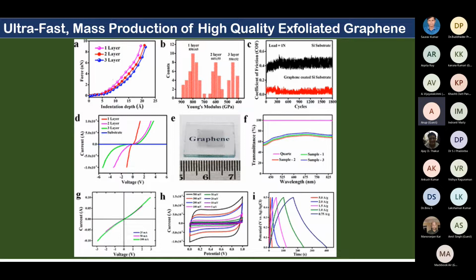But for the uncoated black one, we can see that the coefficient of friction is around 0.4, right? Then we know that graphene has very high thermal and electrical conductivity. So what we have done is we applied a range of voltage and tried seeing how the current goes with our graphene, right? So this blue one is for the substrate, and the layers, you can see layer 1, 2, 3, right? And then we tried doing that. We can see here layer 1, the red one, for a very small range of voltage, how the current is shooting up. But for layers 2 and 3, it needs a little higher voltage.